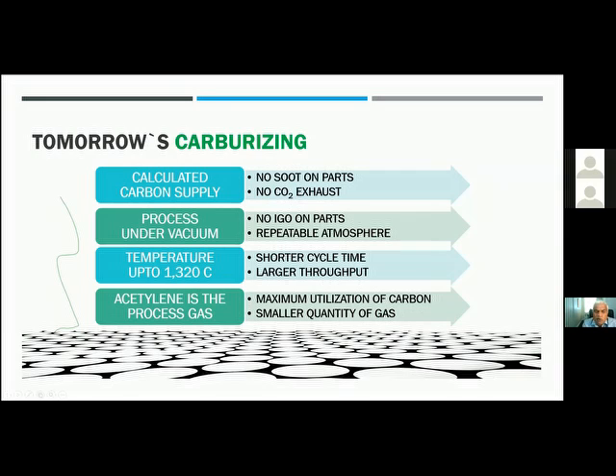Let's come to carburizing as we understand it for tomorrow, which is low pressure vacuum carburizing. The fundamental difference between conventional carburizing and low pressure carburizing is that you provide a calculated carbon supply into the furnace. Unlike conventional carburizing, where you just pass methanol or endogas at a continuous flow rate per hour or per minute, it is not a calculated carbon content. In vacuum carburizing, you actually calculate the carbon content, and I'll show you in the next slide how it is done. This ensures there is no excess carbon, unlike excess methanol or excess endogas. So fundamentally, you get no soot on the components.